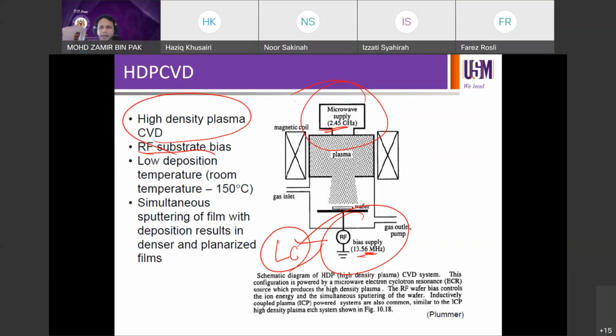With high density plasma, it's plasma enhanced, just like PECVD, except the density is higher. You can even reduce the temperature further. Earlier it was like 200, 300, now you can reduce to 150 and still have CVD going on, right? So just imagine you started off with 1000 degrees C for conventional CVD, you use plasma, you can reduce to 200 to 300, you use high density plasma to enhance the process even more. So you have a window to reduce. The decomposition is enhanced, so you have the option to reduce temperature. That's how you play. The moment you have plasma, you can reduce temperature. If you don't have plasma, you have to increase temperature, else you won't have CVD, right? Simultaneous sputtering of film with deposition results in denser, planarized properties of the deposited film.